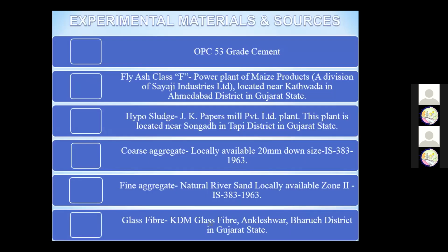based on this design. Now I select the OPC 53 grade of cement, fly ash class F, a power plant byproduct. I select the fly ash near the Sayaji industry, near Kathwada in Ahmedabad. Hypo sludge from JK paper mill near Songadh in Tapi district, Gujarat. Coarse aggregate and fine aggregate locally, and the glass fiber, KDM glass fiber, Ankleshwar, Bharuch. So I select these materials for my work.